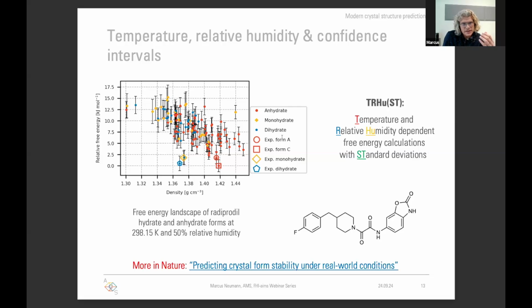Now, crystal energy landscapes have been calculated for a long time by many people. Now, what makes this a modern crystal energy landscape? First of all, if you look at the landscapes, then every predicted energy carries an error bar. And so today we know to which extent we can trust the free energy calculations, and then that of course makes it possible to take decisions based on risk analysis in the production process. You will also see that there are different colors, and the different colors relate to different hydration states. So here we compare anhydrates, monohydrates, and dihydrates.